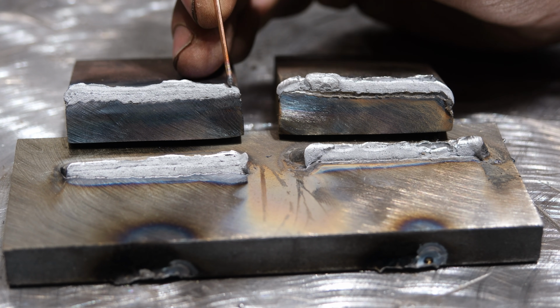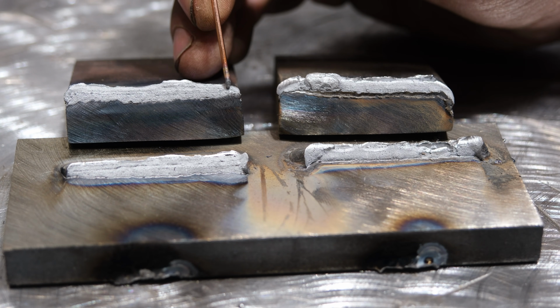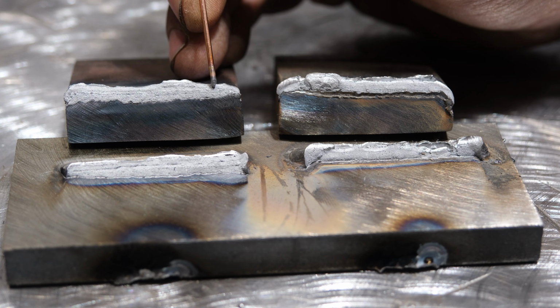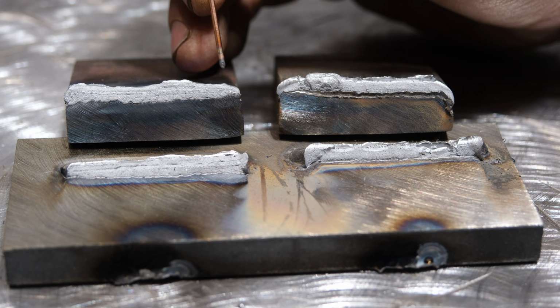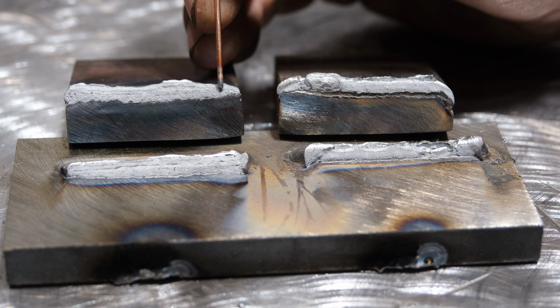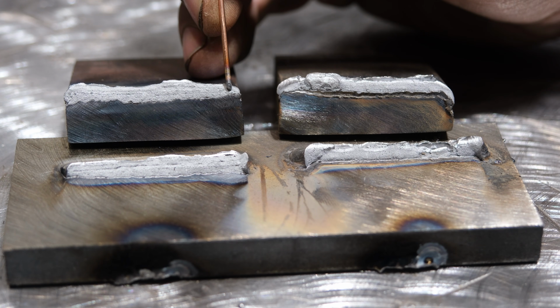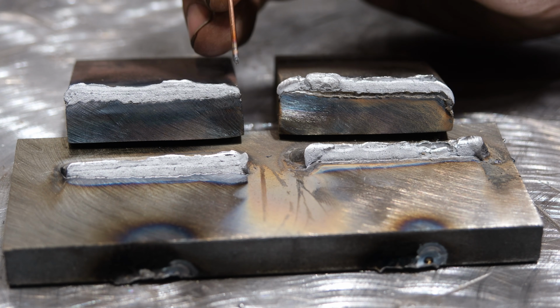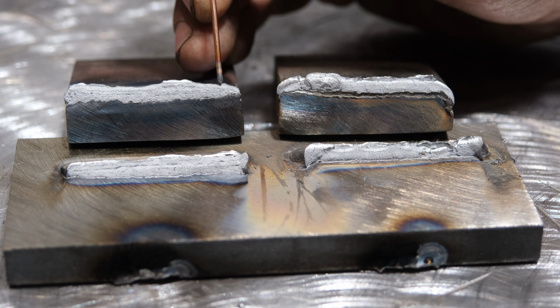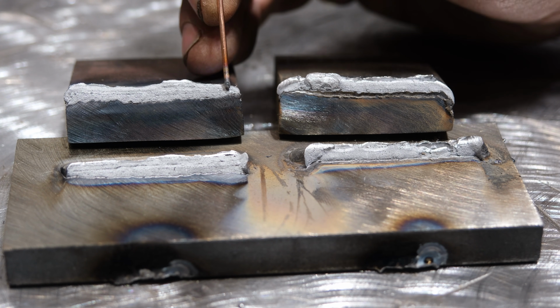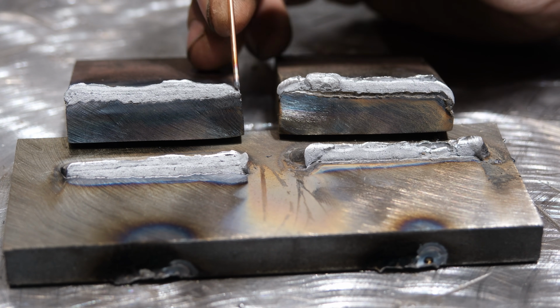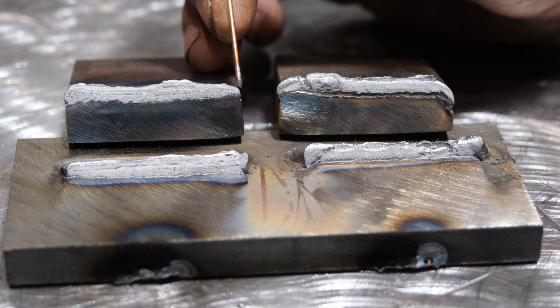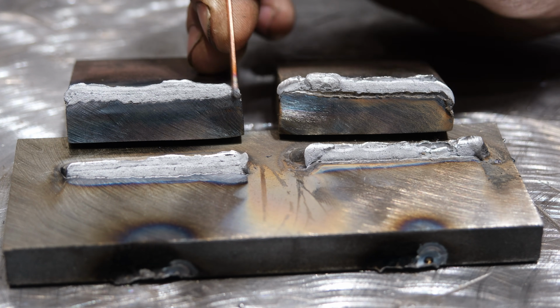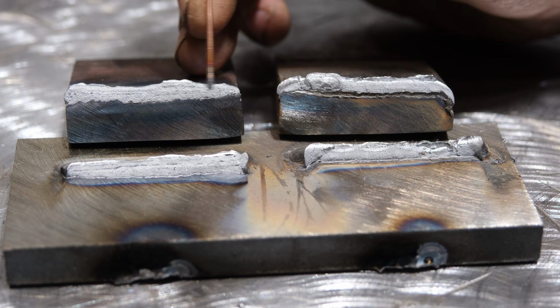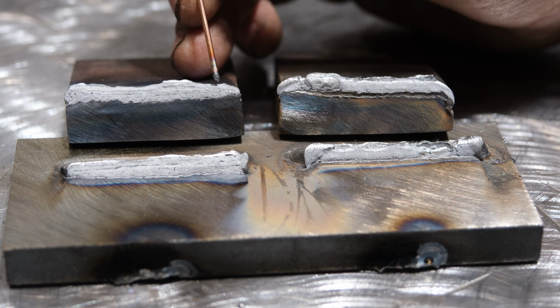And that is because TIG can achieve fusion on even short welds completely in disregard to the thickness of the material. So TIG gives you the ability to make very short welds on very thick materials and have the strongest welds, not because of the filler, but because of how the process works. You can achieve fusion separate from addition of filler. Now, to make this even better than what it was, I should have had a little bit longer of a dwell time at the start, and that would have cleaned this up. But for the most part, this is all looking really good.